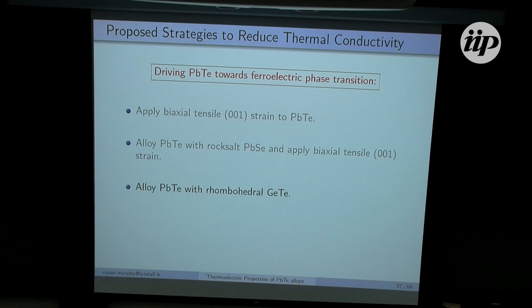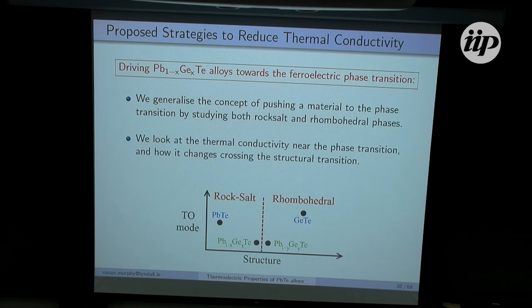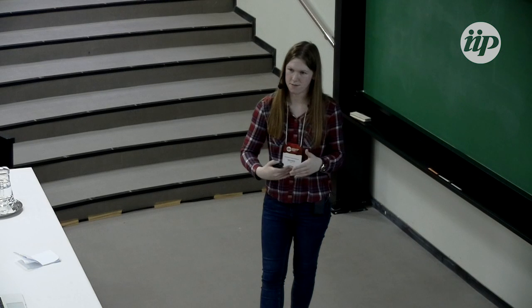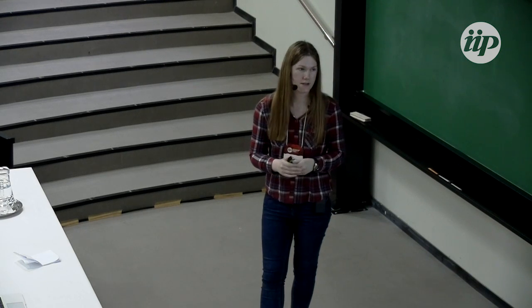So now I want to move on and talk a bit about the third approach, which was to take lead telluride and alloy it with a rhombohedral material, germanium telluride. Now, in this case, you remove the need for strain, and by simply increasing the germanium content, we can push the alloy to the verge of the phase transition.